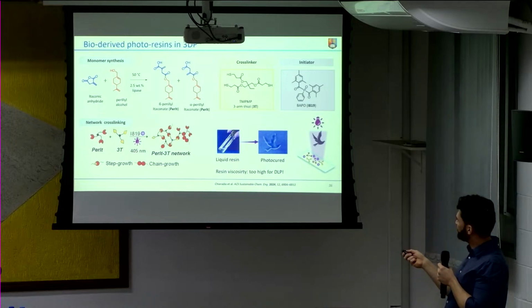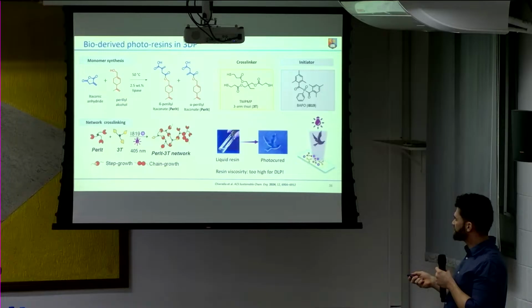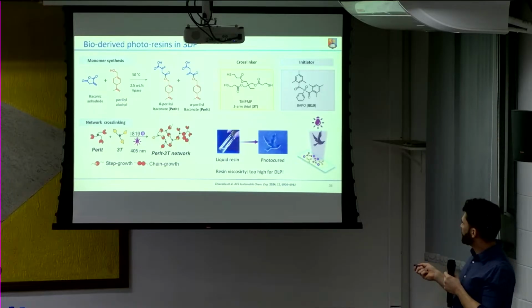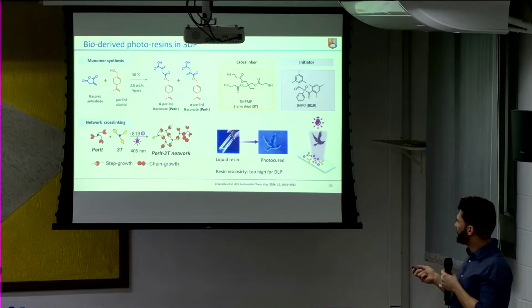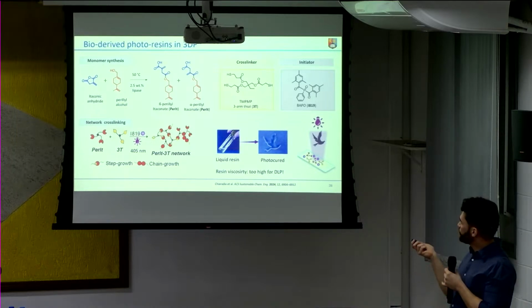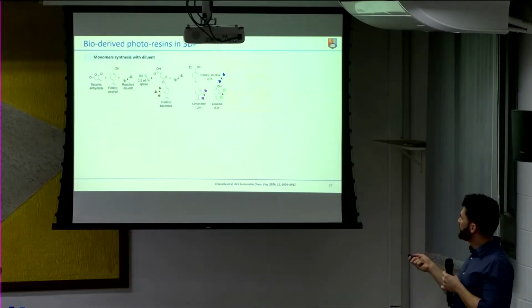And here, because we have this acrylate-like double bond, we have step growth from thiol-ene polymerization and chain growth from the acrylate from the itaconic acid. So it's a mixed mechanism system. So we were able to cure the liquid resin into a photocured film. However, this formulation here has a very high viscosity, too high for DLP. So we had to include some reactive diluents to make it less viscous.